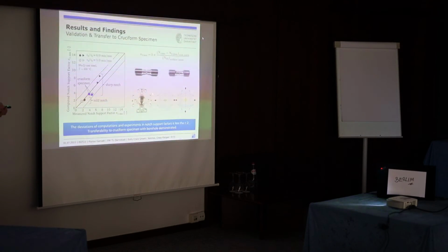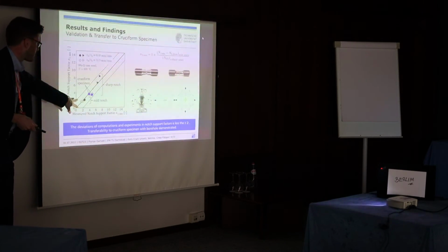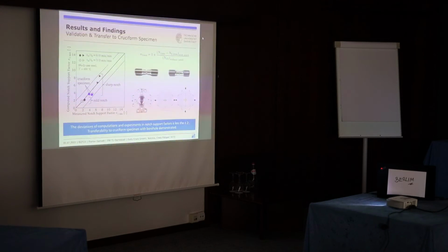You can see here a cruciform specimen with a central borehole acting as a notch. We applied uniaxial and biaxial loading here, and as well for these cases our computational approach worked very well, and we compared the results with experimental results and end up with a notch support factor of around about 4. And this scatter band is plus minus 2, so this is a very good result.